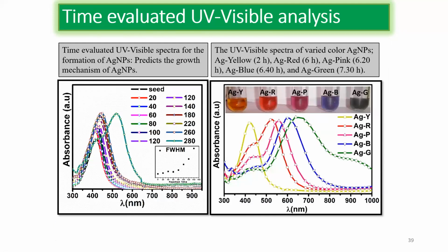So this is a similar type of work to what I showed earlier, where I took two types of spherical and one broadband particle. I thought, why can't I just make some polychromic particles? So I made a little change in the synthesis procedure, and I could make five different colors of nanoparticle: yellow, red, pink, blue, and green. This is just by one pot. I collected the sample at different times, and we can see complete plasmonic tuning.